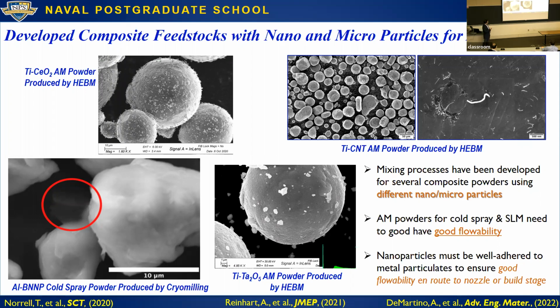You're trying to get it on the surface of the particle, because by themselves, the particles are not going to flow. They're very fine, they're sticky. They're not going to form a uniform powder bed. So they need to be attached to the larger particle, essentially as a carrier. If you have a few loose ones, it's not a big deal, but you want them to be attached, and you don't want to change the shape of the particle. If you start getting platelets, then you have problems.